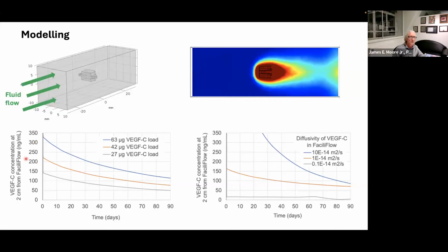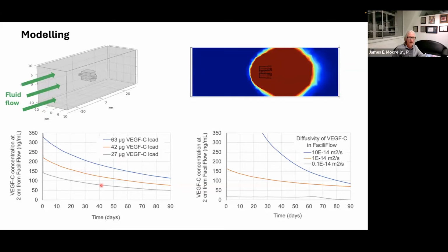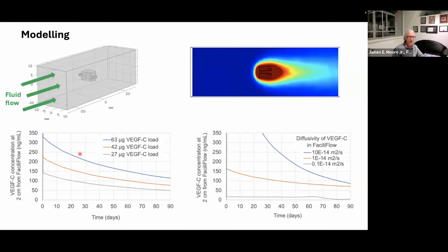Then we can plot things like, 2 centimeters away from the implant, how does the concentration vary in time, depending on how much VEGF-C we have inside the implant. You can see the more you put in, more comes out. It sort of makes sense. Now, the therapeutic level of VEGF-C is about 100 nanograms per milliliter, so about this level here. In order to make sure that there's enough VEGF-C at 90 days, we would need to load it up with about 60 micrograms of VEGF-C. So it gives us a good idea how much we need to load in there.